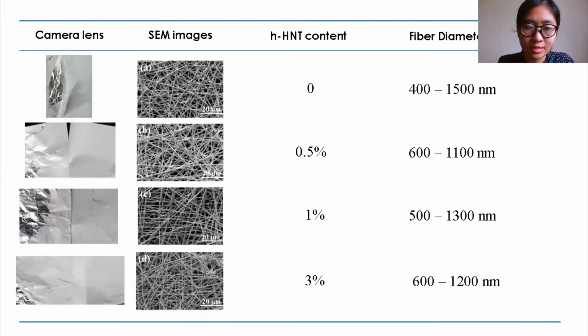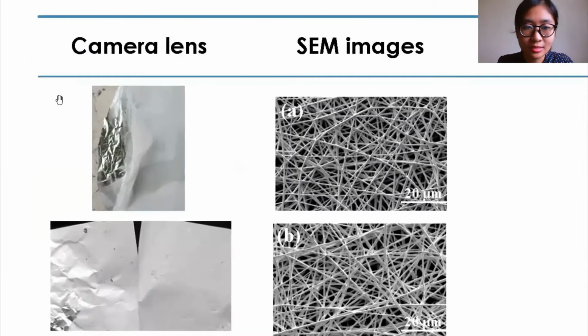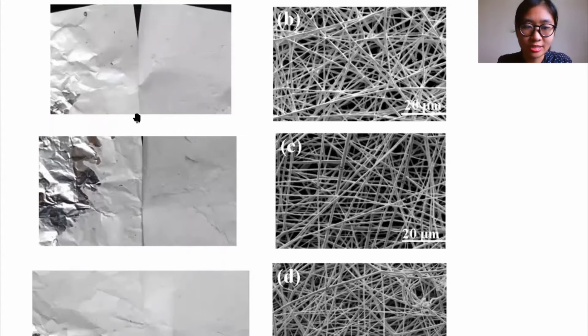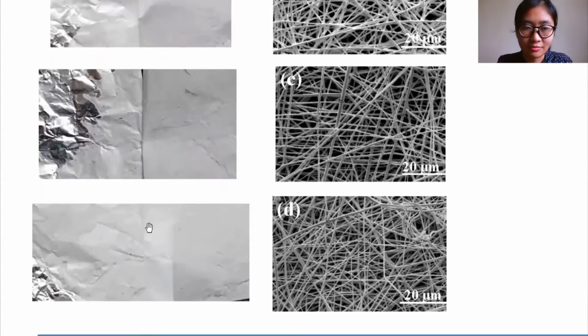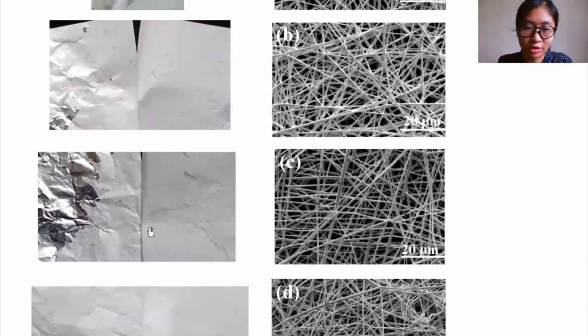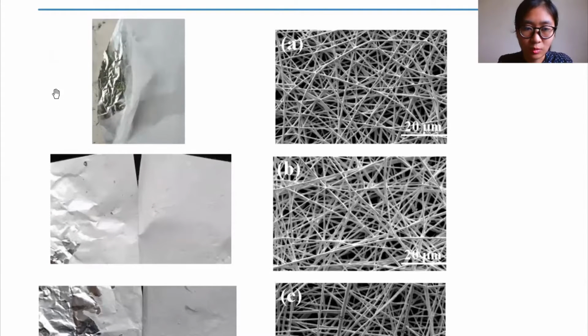So I have included here images captured using camera lens. Let's zoom that in. Zooming in, when I peel this off the aluminum foil, you can see microfiber strands. This is for pure PLA only. And then for the PLA HHNT composite fiber mats, the fibers are not that observed and they have a much firmer structure compared to this one.